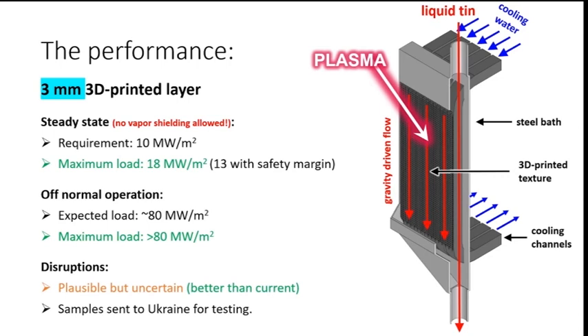So what happens if we go to 3 millimeter? The surface is thicker, it will heat up more easily. That's why in steady state we have to reduce the maximum load to about 18 megawatt per square meter. In off-normal operation, the nice thing is, because the surface is a bit hotter and further removed from the pipe, from the cooling water, vapor shielding now allows us to deal with this 80 megawatt per square meter. So this is fantastic. I should say there is some uncertainty here, so that's why I've put more than 80 megawatt per square meter instead of an actual number, because you need very good estimates of the actual energy dissipated per evaporated particle, this kind of thing.